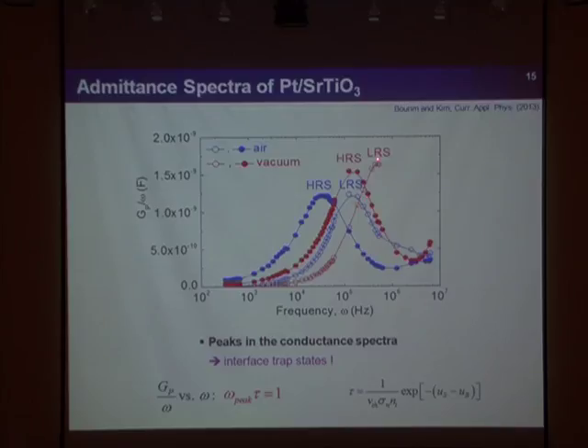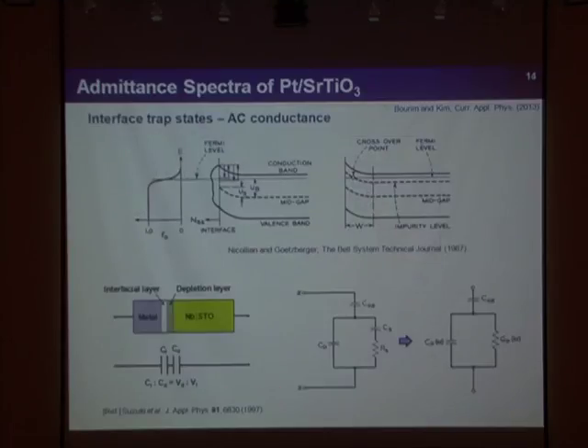The peak position gives us tau, the characteristic capture time, related to the thermal average velocity, cross-section, and intrinsic carrier concentration. US and UB indicate the difference between the surface band bending and the Fermi level versus intrinsic level difference, so roughly that corresponds to the surface band bending term.